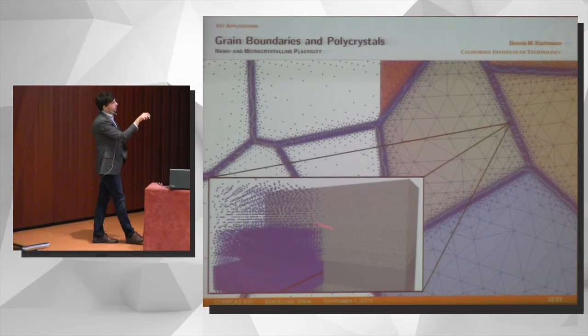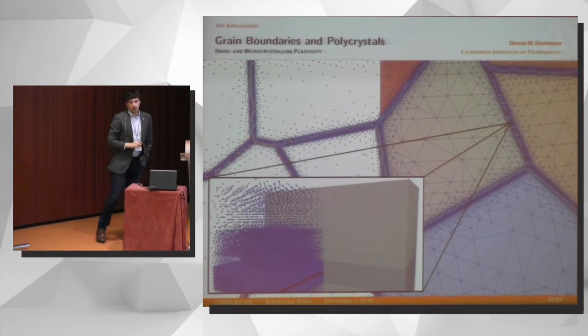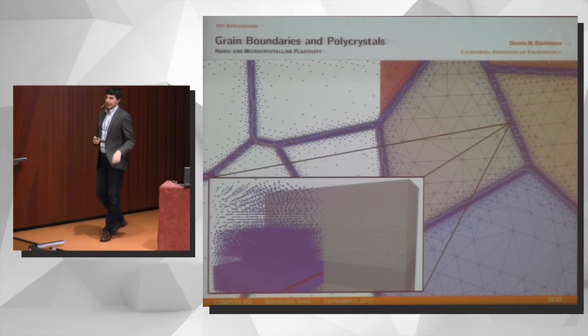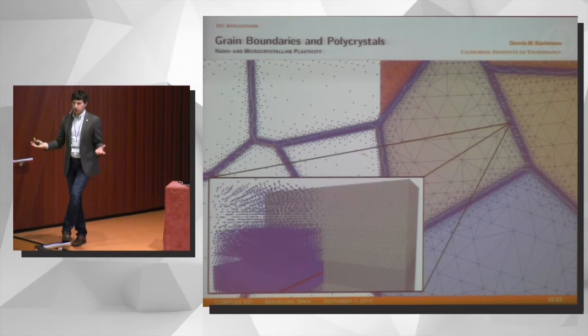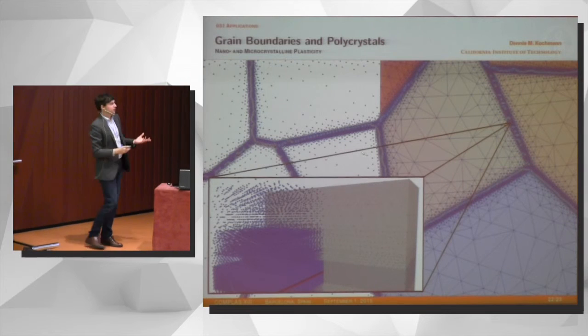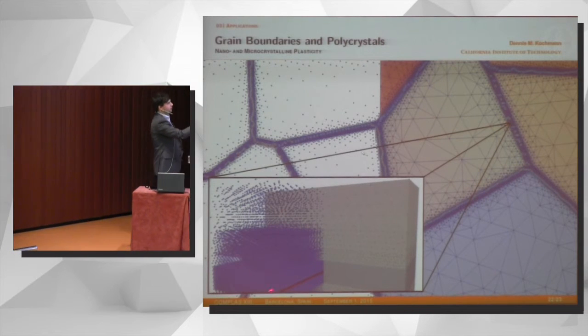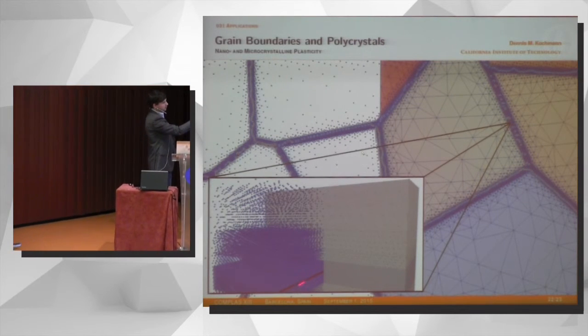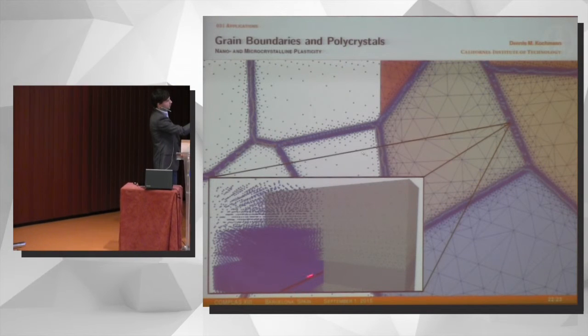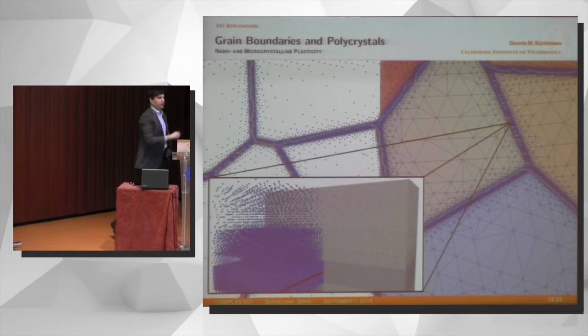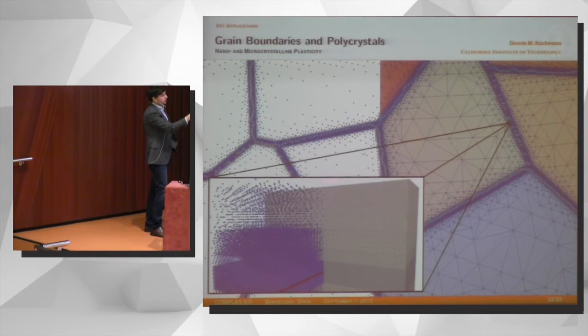Or, even simpler put, you can also do calculation on representative unit cells. Let's say you want a continuum model and you need to know what the grain boundary energy is. In this case, we can easily set up a unit cell which has a grain boundary at the center. This here is a simple sigma 3 boundary, one grain at the top, the other grain at the bottom. But we don't need full atomistics for this.